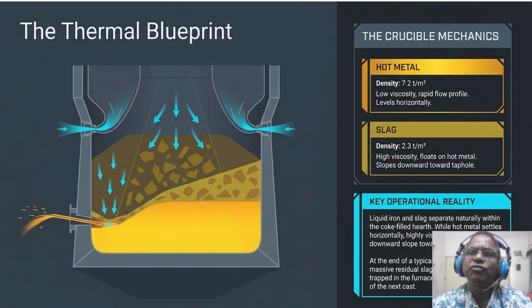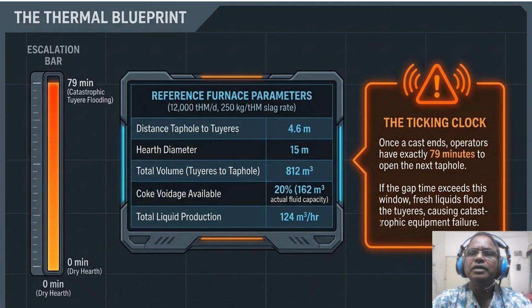The factor here is the residual volume. At the end of a typical 60 to 240 minute cast, a massive amount of slag remains trapped because of this slope. This is not just leftover material, it dictates the intermediate urgency of your next cast. If you miscalculate the slag slope, you miscalculate your available hearth capacity, leading to a dangerous reduction in internal voidage before the next hole is even drilled. This residual volume is the primary driver of your most critical metric, the time remaining until catastrophic failure. So every minute the taphole is closed, the clock is ticking.